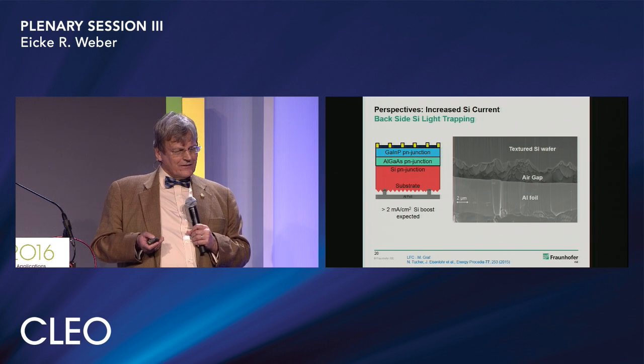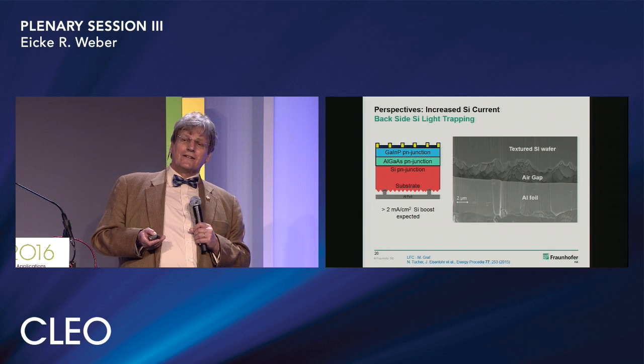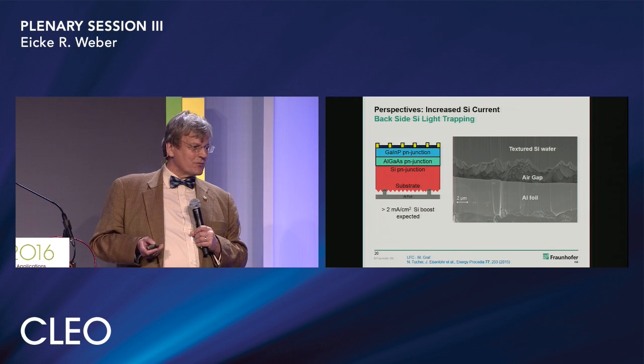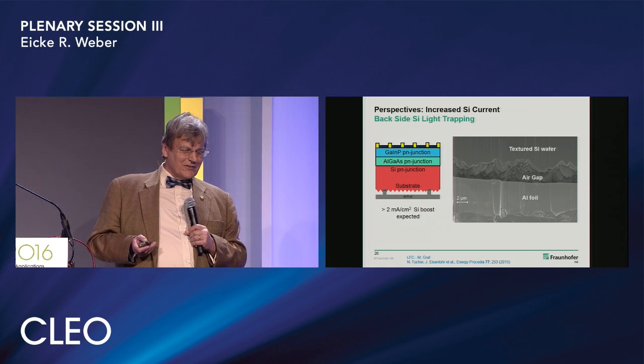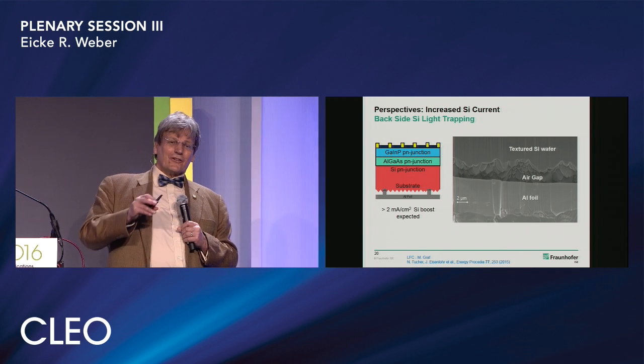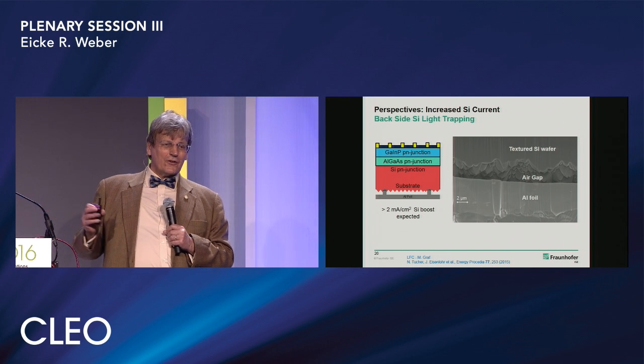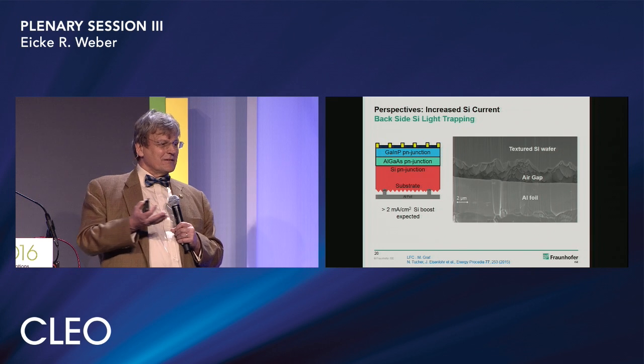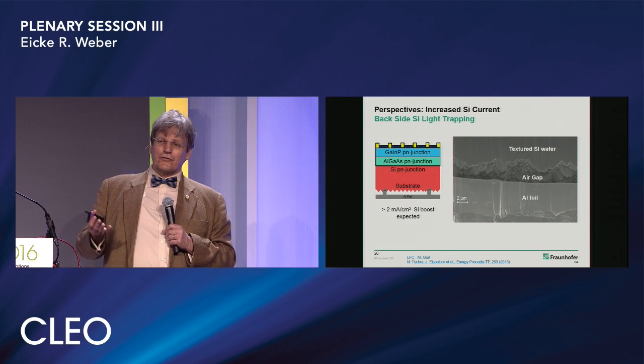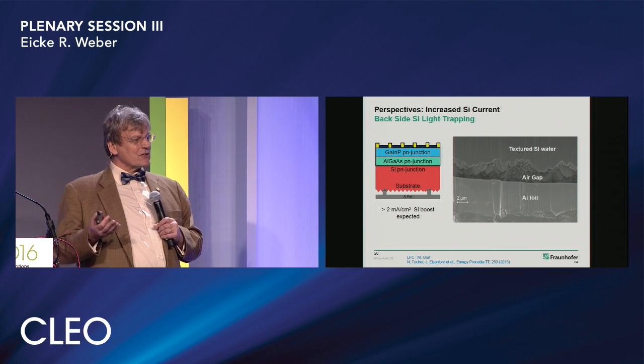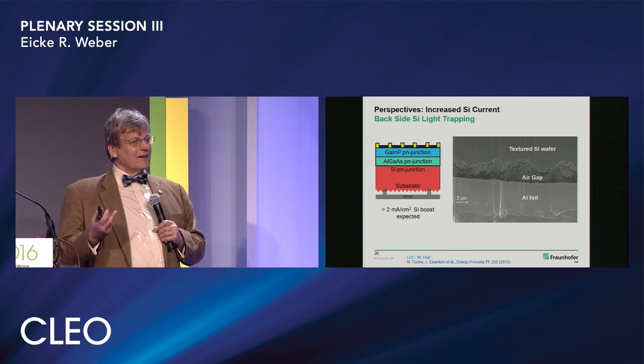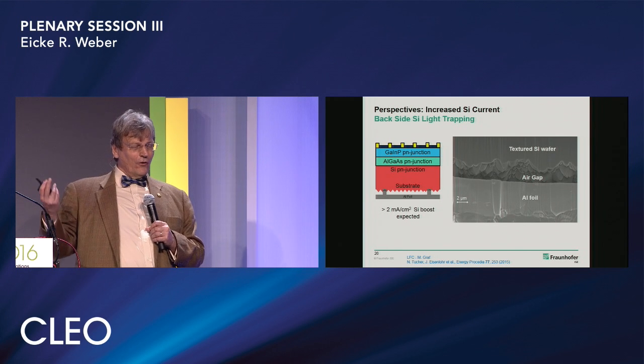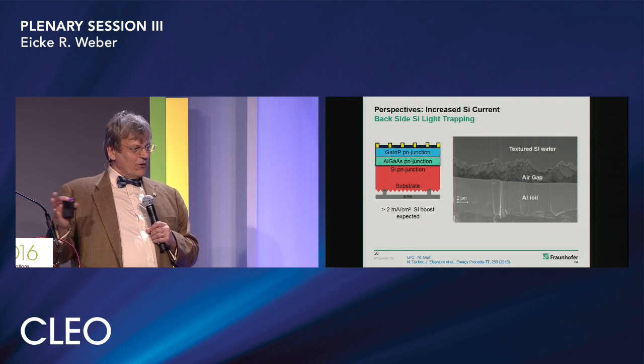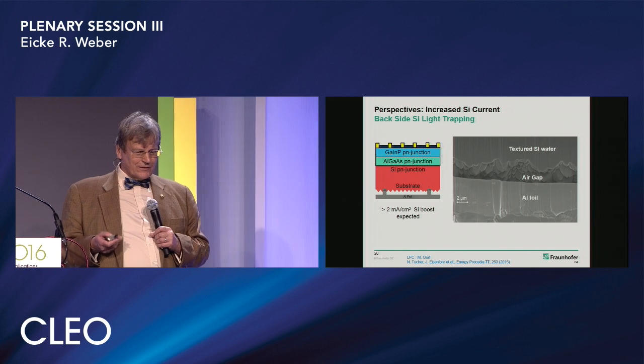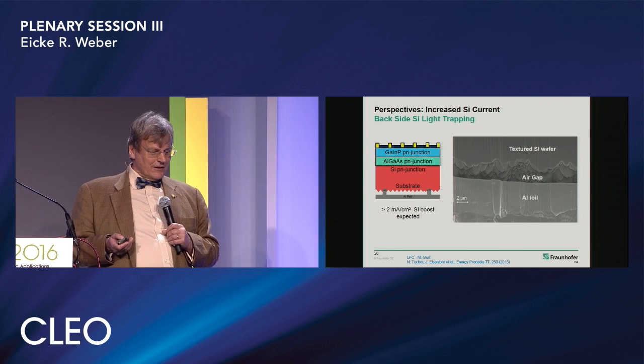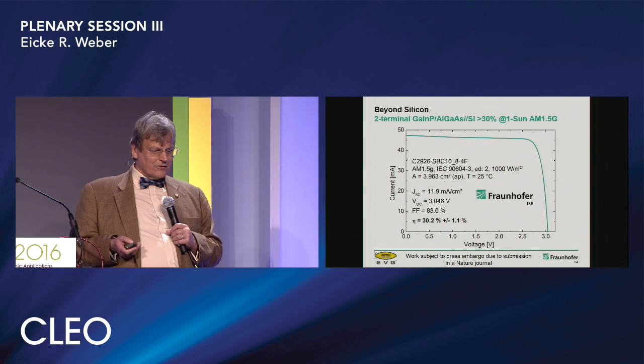You see the contacting with an aluminum foil, a technology which was developed at my institute. It turned out that contacting with an aluminum foil is almost as good as depositing an aluminum layer, but of course it interferes much less, it gives much less recombination centers. You bond the foil with a laser at thousands of bonding posts across the wafer, and in this way you guarantee the good electrical contact.